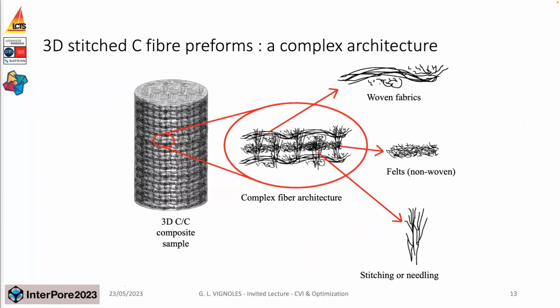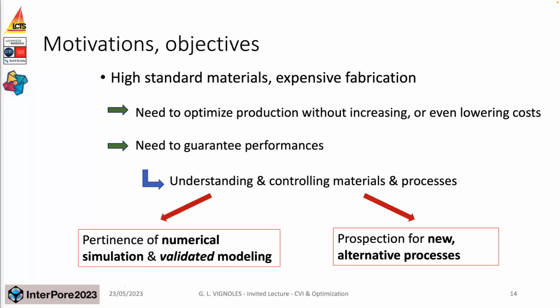This is an example of a carbon fiber preform. It can be very complicated. You have woven fabrics, but you also may alternate them with felts, which are non-woven, and you can have some needle punching of all that, so it makes them a very complex fibrous medium. So the motivations here are that these materials are extremely expensive in their fabrication, so optimizing the production is very important for the industrials, of course, and you want to lower the costs. But the performances should be guaranteed, and in particular, we will see the deposit uniformity. There's some pertinence of having a very good numerical simulation that has been consistently validated with respect to experiments. And when you have that, you can also prospect for alternative processes.